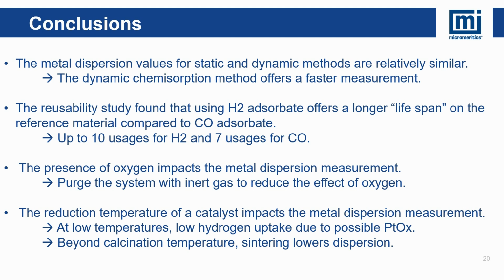Case study 2 highlighted that the presence of oxygen can affect dispersion measurements. A key recommendation for our viewers is to use a high purity inert gas to purge the system after the activation process to minimize such effects. Lastly, case study 3 showed that the dispersion values were influenced by the reduction temperatures. As expected, pretreatment at temperatures beyond the calcination threshold resulted in platinum particle migration, which effectively reduced the number of active sites available for catalytic activity.